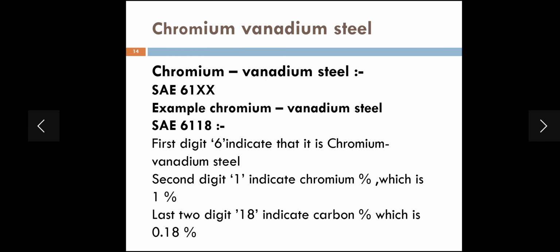Now the next steel grade is chromium vanadium steel. The example of this steel I have taken is SAE 6118. Here the first digit is 6, which indicates that it is a chromium vanadium steel. The second digit 1 indicates the chromium percentage in the steel is 1% of chromium. And the last two digits 18 indicate the carbon percentage, 0.18% carbon in the steel.